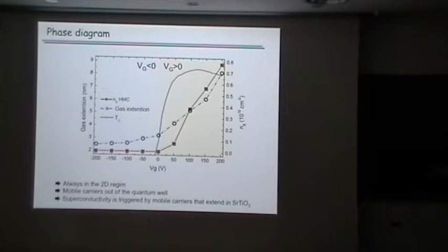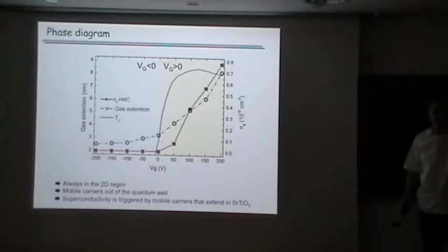Okay, I won't put my hand in the fire on those calculations in detail, but I think the basic principles are here. You can see, for instance, this is the extension of the gas in this model, which is fairly flat here in the negative part and rises up at the positive part. And here, this is what we got from the number of highly mobile carriers from the Hall effect, which rises up at the same time. And you also see that Tc goes up at the same time.